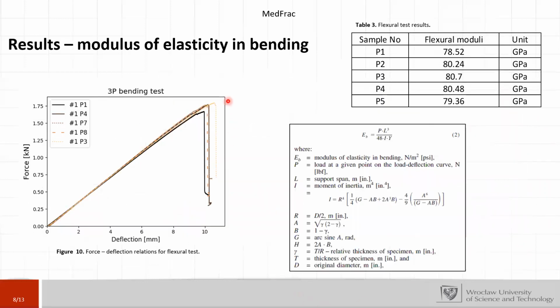Then the results for the modulus of elasticity in bending. In figure 10 you see the force deflection relation for the flexural test. And here it's possible to see the equation for the modulus of elasticity. We use it according to the ASTM standard, and we see that the average result for the flexural modulus is approximately 80 gigapascals.